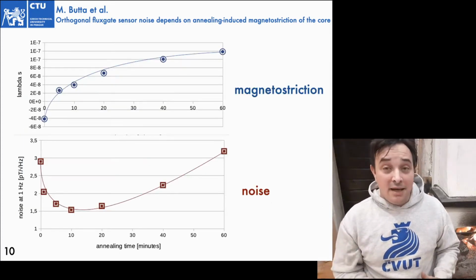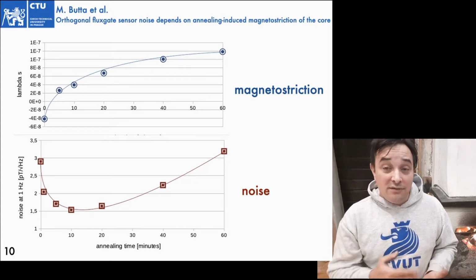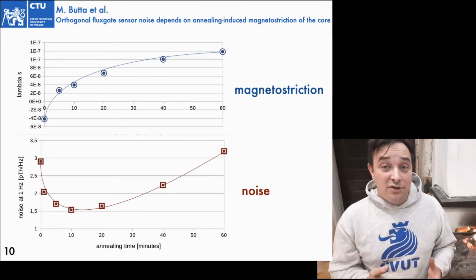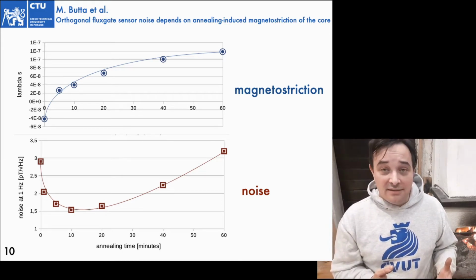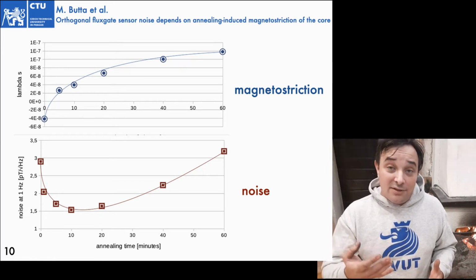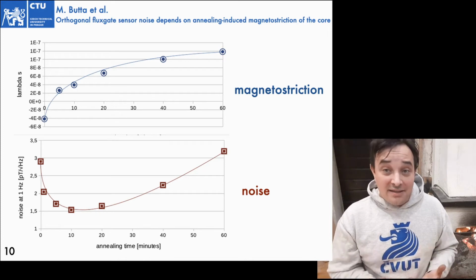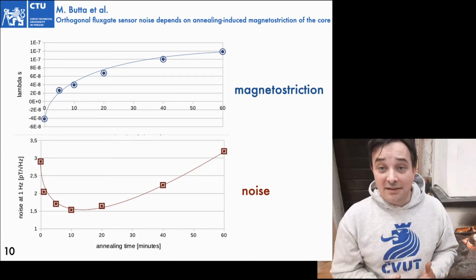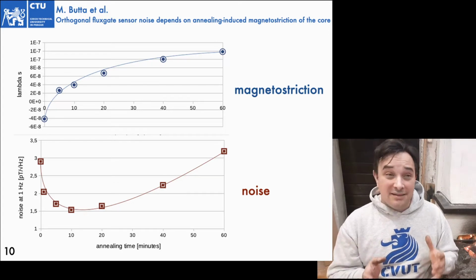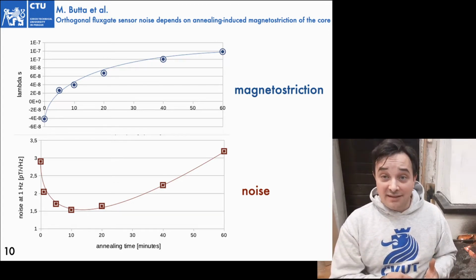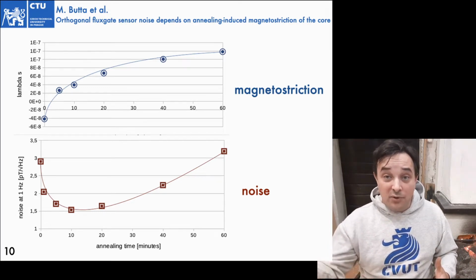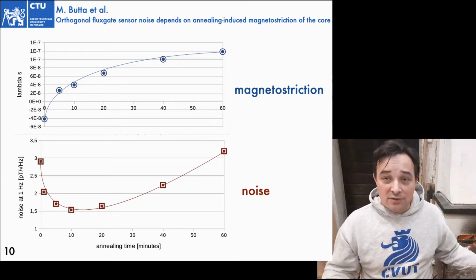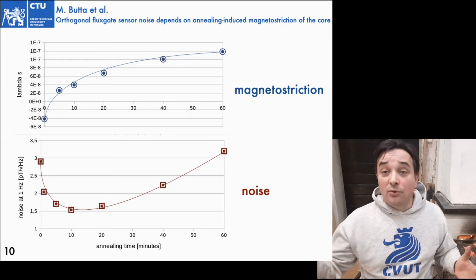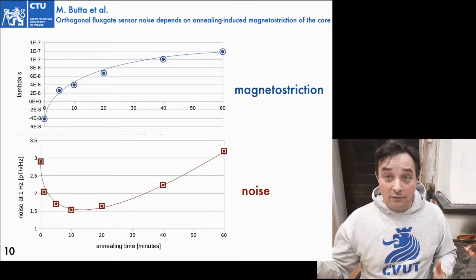So we took our wires and we have measured the magnetostriction for different annealing time. As you can see in this graph, we achieve a very low magnetostriction constant, kind of -4 10 to the -8 for as-cast wire. And then this magnetostriction, as described in the paper by Vasquez, increases monotonically as we increase the annealing of the wire. In fact, our wire has a slightly negative magnetostriction when we consider it as cast. But then, annealing the wire, the magnetostriction increases, becomes 0, and then becomes positive, up to becoming from -4 10 to the -8 for as-cast wire, up to 1.2 10 to the -7 for 1 hour annealing.